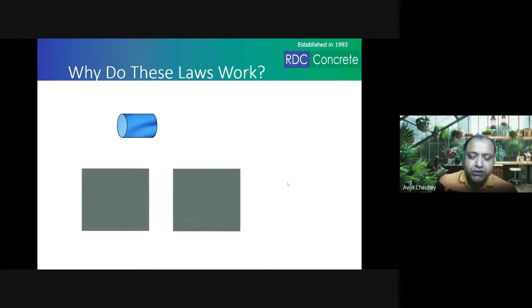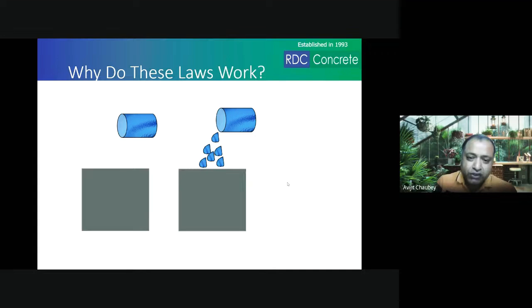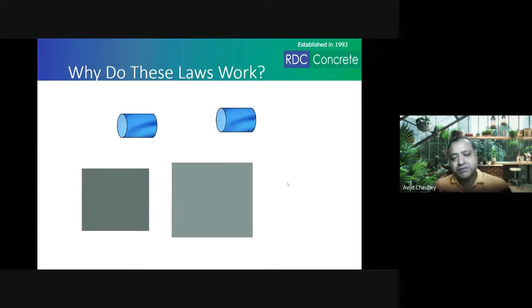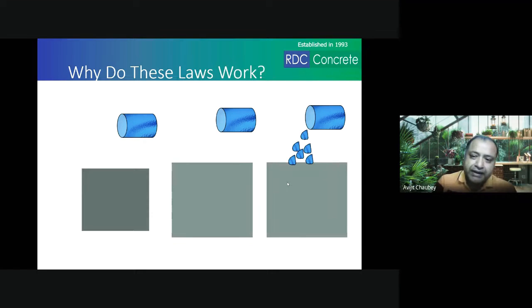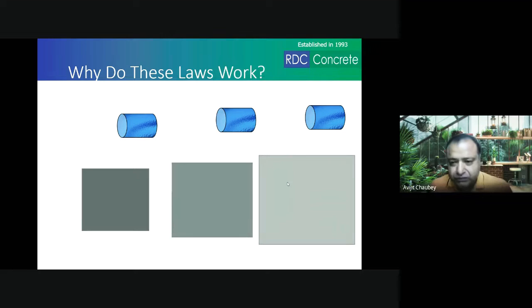And then what you do is you take a similar kind of clay, you put similar amount of water, but what you do is you add in more amount of water. And similarly, the third case you take, and in the same clay you add even more amount of water. If you see, the difference between these three pastes, visually, would be that the third one, where the water content is very high, would be a little lighter. It would be a little less denser. The third one would be light in color. The first one would be much darker in color.